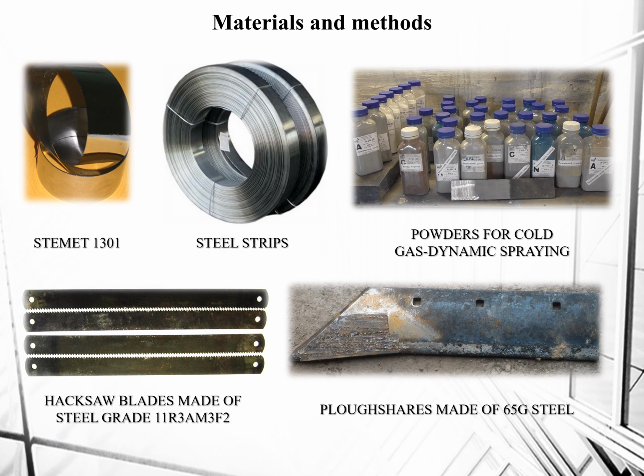Before welding, the connected surfaces of the main and additive materials were subjected to abrasive blasting operation. Abrasive blasting of the surfaces was performed with DIMET KO416 corundum powder. Stemet 1301 nickel-based amorphous tape solder was used as an intermediate layer. As an additive material, the following were used: spent hacksaw blades made of steel grade 11R3AM3F2 with a thickness of 2 mm, as well as steel strips with a thickness of 0.5 mm made of steel grade 65G, U12A, 50HFA. As a basis, samples made of strips of grade 65G steel with a thickness of 12 mm were used. For reference, a sample made of 45 steel was used.